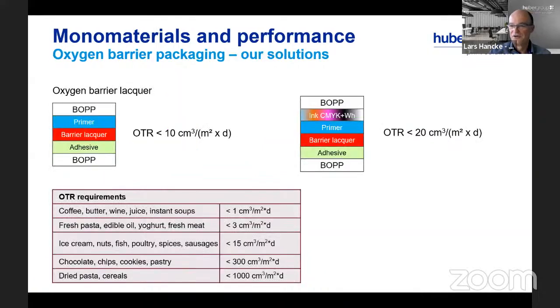And like Köhler, we have also looked on the film side at how we can improve the barrier properties, mainly focusing here on the oxygen barrier properties. And we have developed a water-based oxygen barrier lacquer, which we combine with a solvent-based primer to have optimum wetting properties and to avoid any pinholes. And when we put that inside a laminate without printing ink, then we get single-digit oxygen transfer rates. Combined with printing, we are a little bit higher. And of course, this depends on how much you apply.